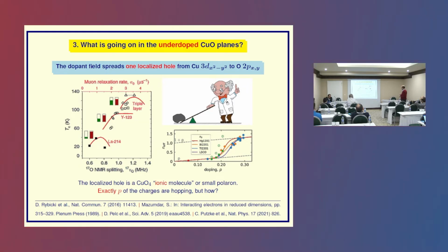And you can clearly see how you go from the low Tc, like LASCO, to the high Tcs, how this transfer happens. Essentially, all of the material dependence in the cuprates is in this localized hole, which is shared between the coppers and the oxygens. And this is my image of this Coulomb lever, which starts with the dopant and then finally pushes the hole onto the oxygen. The consequence is that you have a localized hole as an ionic molecule or a small polaron, and now exactly p, the remainder of the charges are hopping.